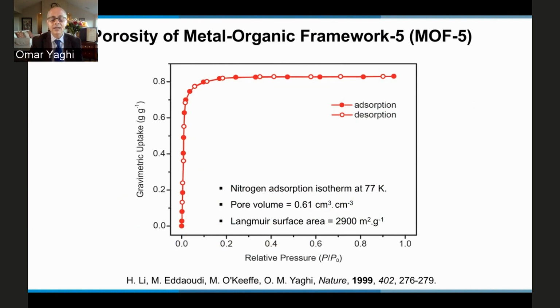In fact, the BASF number was higher. In our lab, our numbers hovered around 2,900 square meters per gram, and in the hands of Ulrich, that surface area was around 3,000 or 3,300. Nowadays, because we learned how to evacuate the pores of MOF-5, the optimal surface area is close to 4,500 square meters per gram.